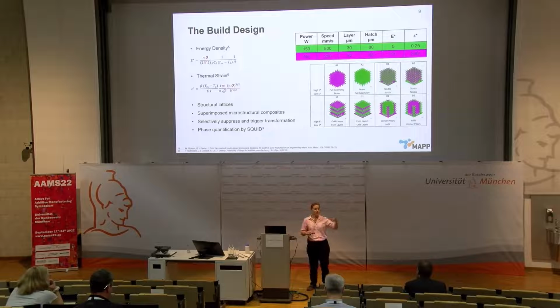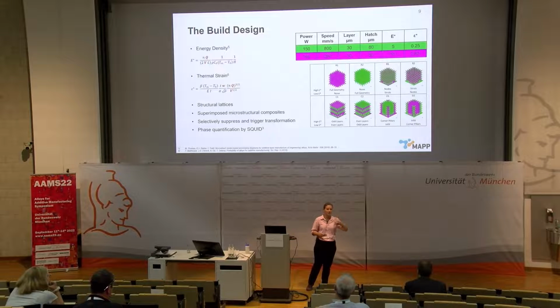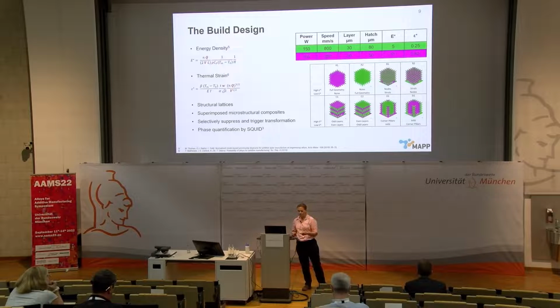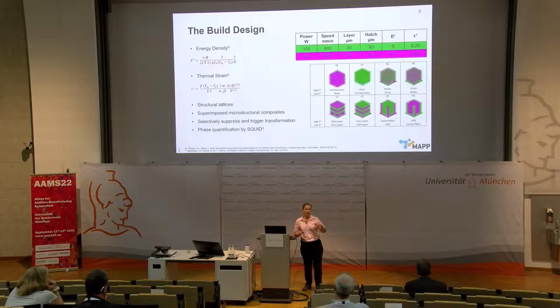So the talk immediately before me, we were talking about residual strain as a problem, and I'm looking at it as a way to change what's happening, a parameter that I can use to tune what's going on. One aspect of this, the phase quantification we've had to do, is using SQUID. SQUID is a magnetic technique, and it has been useful for us here because we've been able to use it without having to do lots of surface preparation, and surface preparation would add additional transformation. So there's quite a lot going on here.